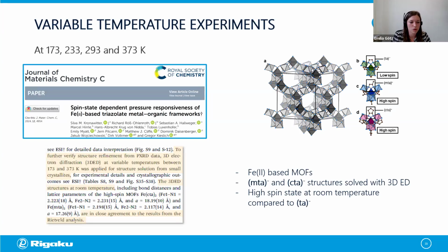But of course, not only pure cryo measurements are possible, you can do variable temperature measurements as well, like in this publication by Kronavita et al. about the spin state of certain iron MOFs. And here, the same grains of the respective MTA and CTA MOF were measured at 173, 233, 293, and 373 Kelvin to observe changes in the structure. And here it could be discovered that these two structures are in a high spin state compared to the low spin state TA structure at room temperature, and that the modification in the MTA and CTA compared to the TA has a significant impact on the void fraction in the structure.